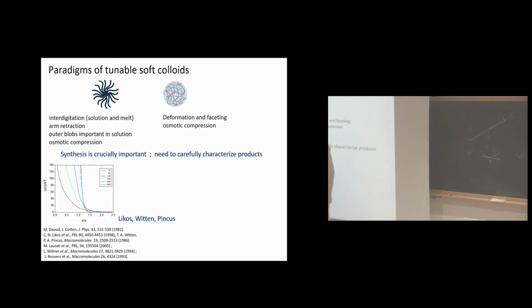No, this one here, I didn't mention because of time, this here is a coarse-grained potential, a pair interaction potential. It's a model, right? Okay. And the main person here is Likos, and actually this is the reference, this PRL here. However, there are simulations which are in full agreement, and there are experiments which are also consistent. In fact, in that reference, the 1998 PRL, there are experiments with neutron scattering on the structure factor by Richter's group in Germany. And so then the structure factor extracted for that potential is in perfect agreement. Okay. So in a way, one can say that this is, I think, reasonably well established.